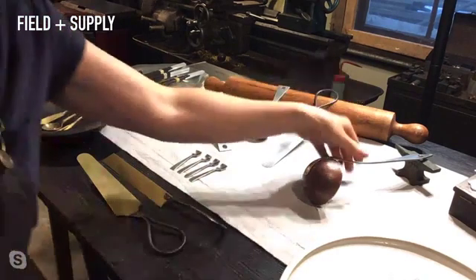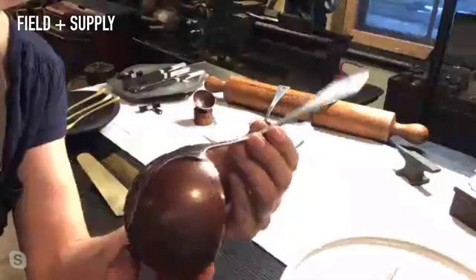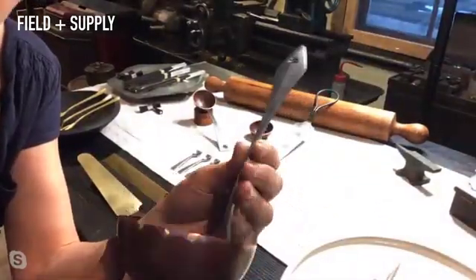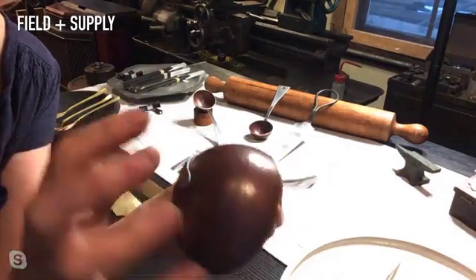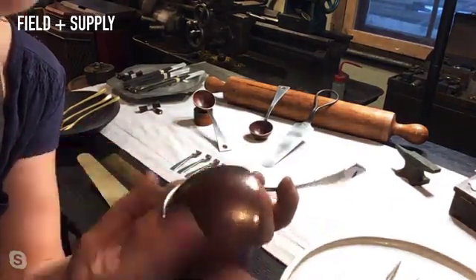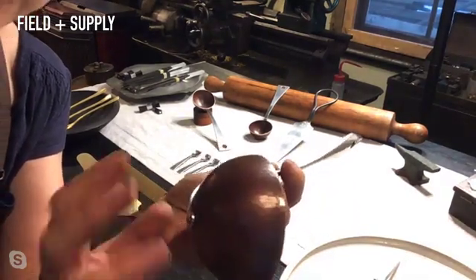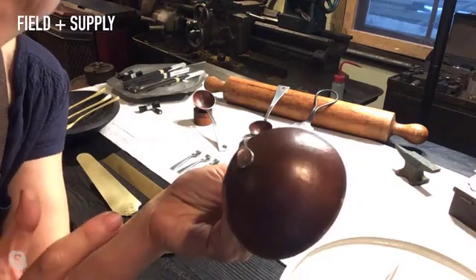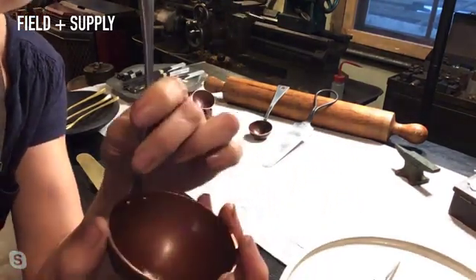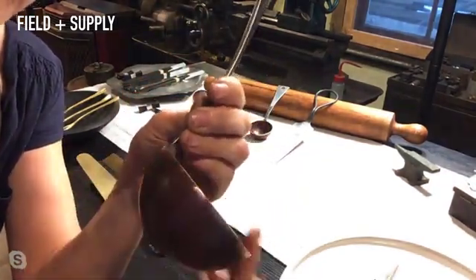So beautiful. This is the ladle. The pieces are over there on the work table. So you have the forged copper. I start with a spun bowl, and then I forge it to stretch it out a little bit bigger, and when you're heating it to do that, it softens. With copper and brass, the only way to get it hard again is to work it. So for it to keep its nice rigidity in here, I peen it to strengthen it again.